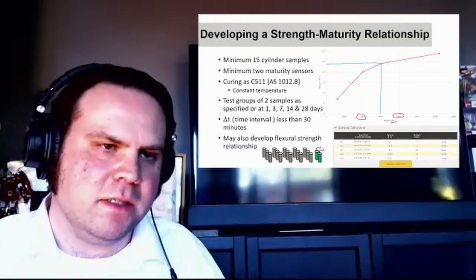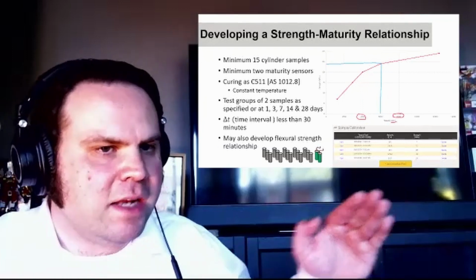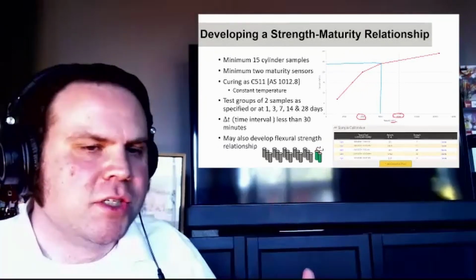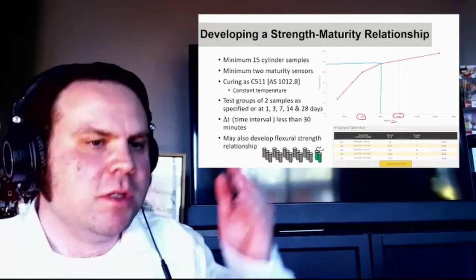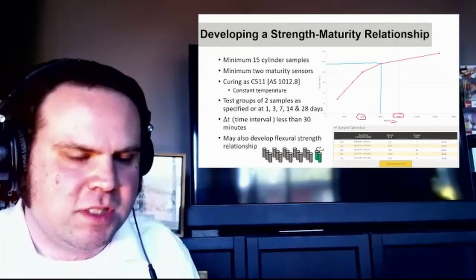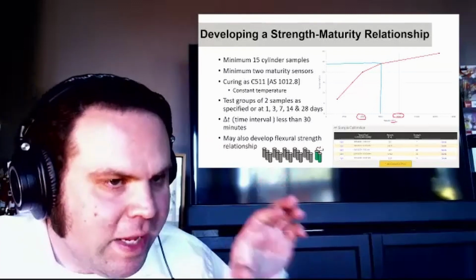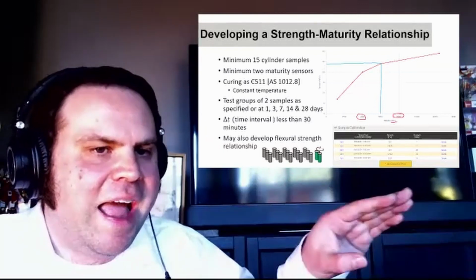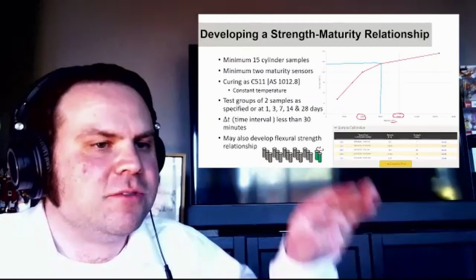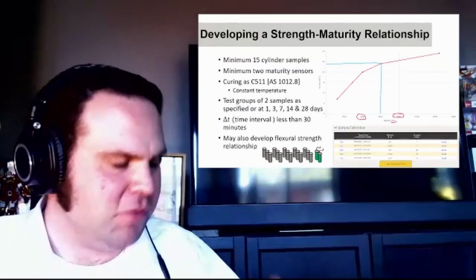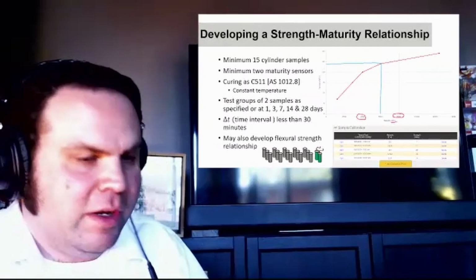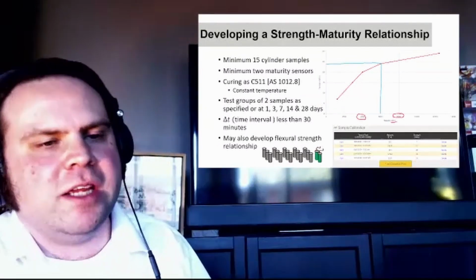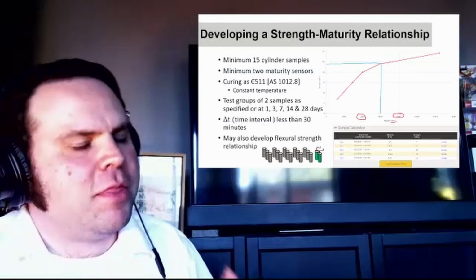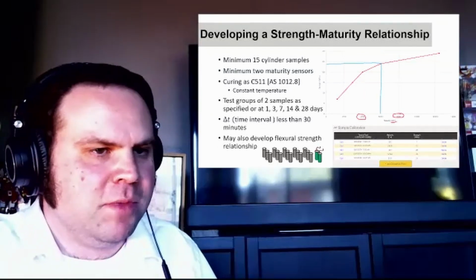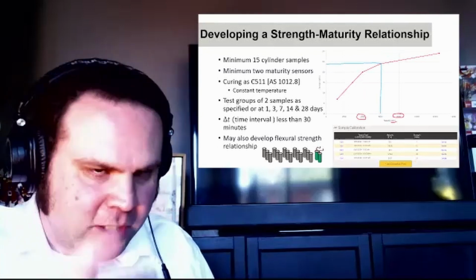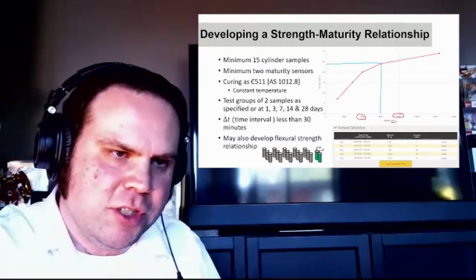That's absolutely the intent. The intent is you create under very controlled conditions your relationship formula, maturity factor to strength gain. Then you use that by putting temperature sensors on your in situ concrete to catch if its strength gain is fast or slow. So if you've got a cold cast for some reason and it stays at a temperature, let's say it was at 15 degrees over the time of its curing, rather than the 23 degrees that your samples were, the gain of maturity index, because they all calculate on time and temperature, will be slower.